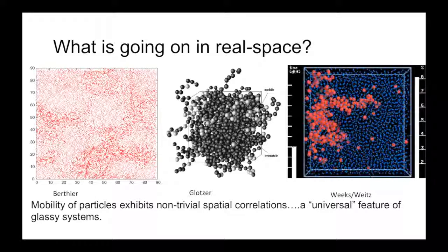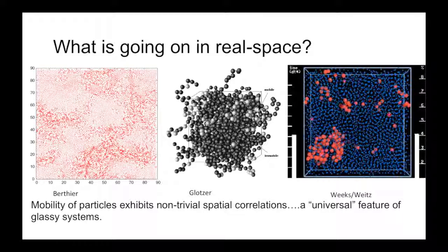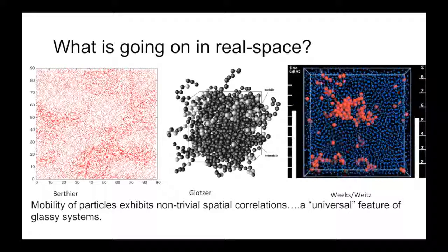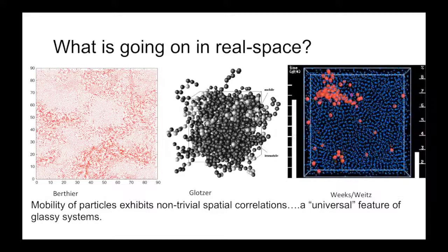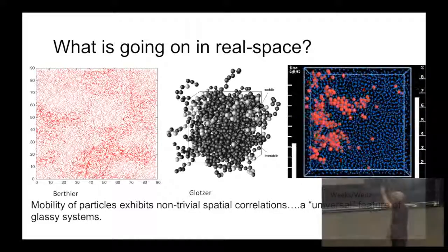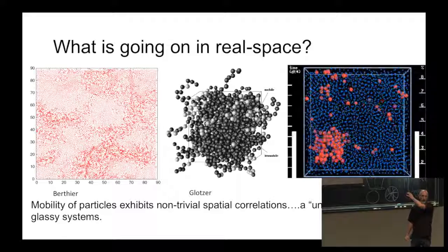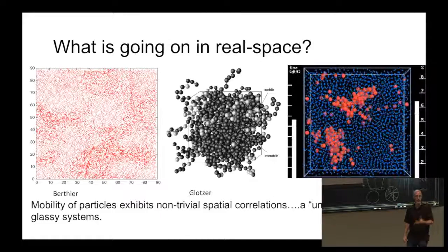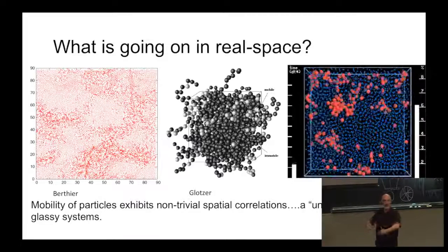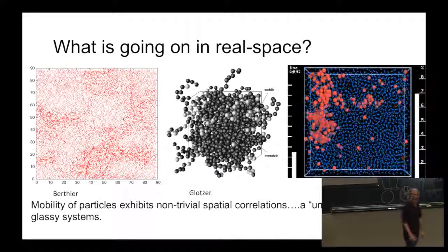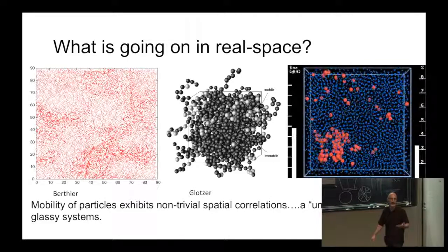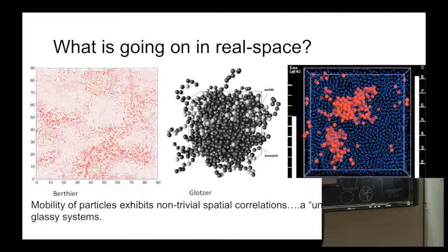So, obviously what you see looks rather dramatic. You see evidence of this jump-like motion that presumably was associated with those distributions that I showed you on the other slide. But you also see that the jumps aggregate spatially, so there is some sort of avalanche-like behavior where particles move together. There may be some collective aspect to this jumping motion that isn't just randomly picking a particle and making it jump further than you would guess by some sort of Brownian model.